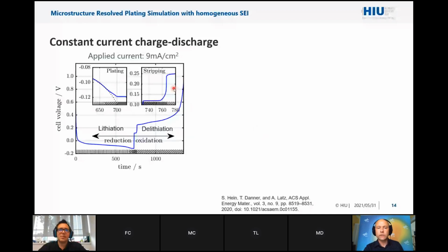And of course, one interesting thing, since you cannot look into the operation of the battery, is do you have some macroscopic features from the voltage time curves, for example, or voltage SOC curve, which give you an indication that you have plating. And what you see here is that, yes, at a certain point where you get a plateau, you have plating. This dotted line is the simulation without the plating mechanism implemented. And you see already deviation from the actual mechanism without plating way before you find the plateau.